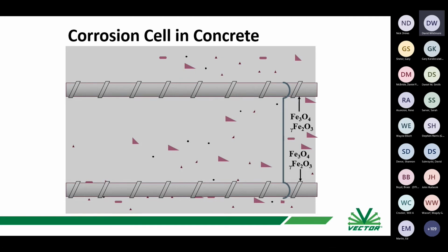You've got fresh concrete and it's highly alkaline, and you'll have the formation of what we call a passive oxide film. If you want to know what the chemistry of the film is, it's a combination of Fe3O4 and gamma phase of Fe2O3, which no one's going to remember. That film is stable in a high pH chloride-free environment, and it will last well over 100 years. You'll see lots of evidence of where this protective film is still in place out on the bridge here, which is more than 100 years old.